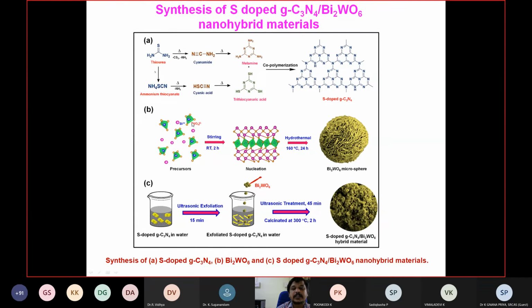Then he took bismuth nitrate and added it with the tungstate precursor. Then it was subjected to stirring for some time, then hydrothermal treatment. Finally, we got the bismuth tungstate microspheres. Then he took this in water and sonicated for some time. Later he added this to the solution, subjected it to ultrasonic treatment, followed by calcination at 300 degrees. Finally, we end up with the hierarchical structure of sulfur-doped graphitic carbon nitride and bismuth tungstate nano-hybrid materials.